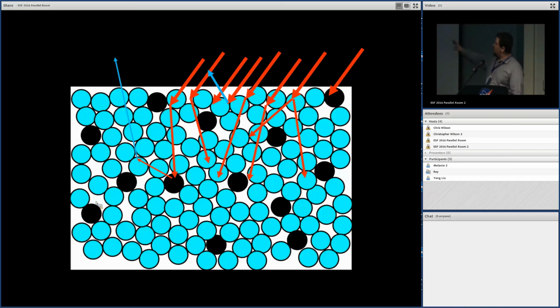And then really this was to show that if I could delete all of the blue spheres here and replace it with a blue rectangle and have the same idea, where we have a very transparent thing that's not absorbing, that's allowing light deeply into the sample, not absorbing strongly. As it's scattering light in different directions, that incident beam is losing intensity and is less likely to hit something and bounce back out the deeper it gets into the sample. It's a very, very simplistic multiple scattering model. Great, thanks.